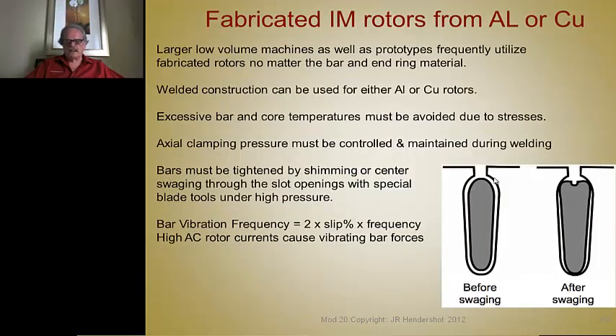Now the bars themselves, as they go down into the slots, if you're fabricating, you have to have clearance. So you'll notice here that there's clearance around the bar, and that'll allow the bars to vibrate. And the bar vibration, and the high AC rotor currents during starting of grid-powered motors at least, cause bar vibrating forces that will cause them to fail eventually. So what you do about that, typically they swage them in. They use a heavy tool and a hydraulic press, and they apply it here, and they mash this down, which forces it at the bottom of the slot and spreads it out here, tightening up the bar.